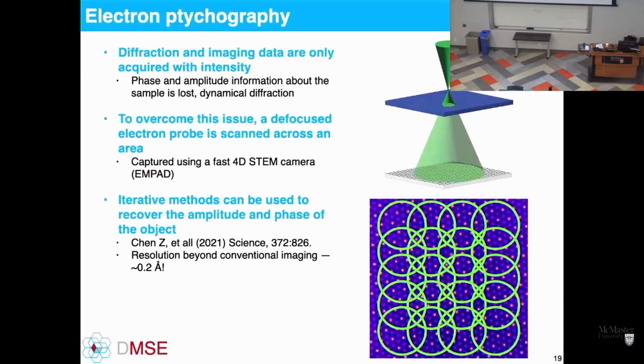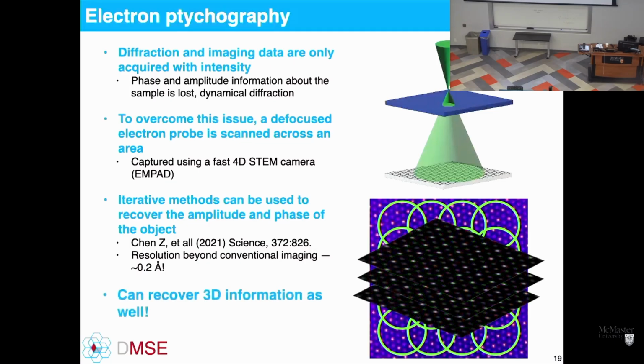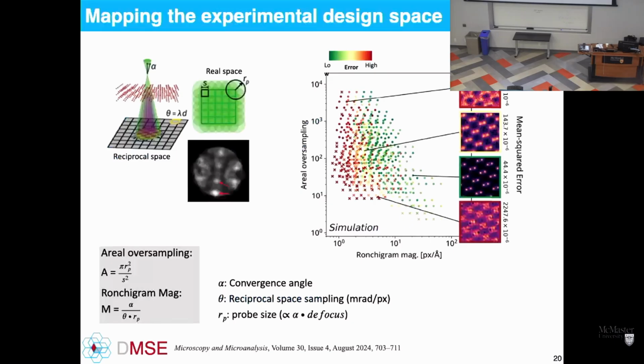So from that one data set, as was shown in the Muller group in this Science paper in 2021, for example, resolution gets down to, of this technique, you're essentially deconvolving dynamical scattering and deconvolving the electron probe. You can go down to 20 picometer-ish resolution of your object. And because it's dynamical scattering, this encodes three-dimensional information within that data set, and you can recover that 3D information as well by resolving this onto a series of slices. So it's not just one image, but one data set can give you 20 images, 30 images from the same object, all with different information.